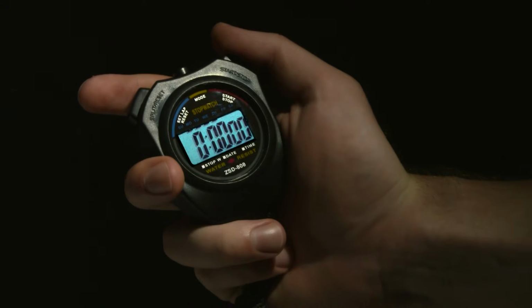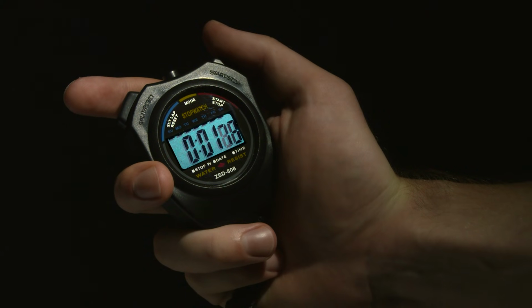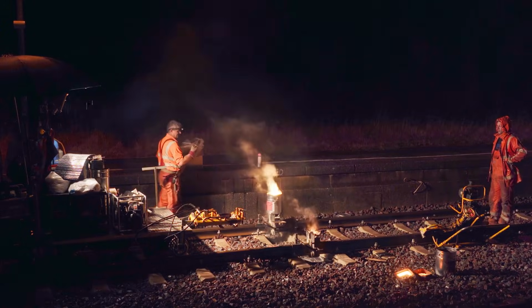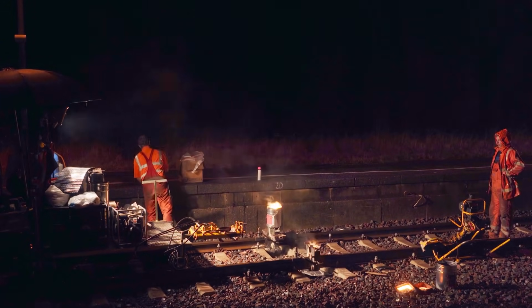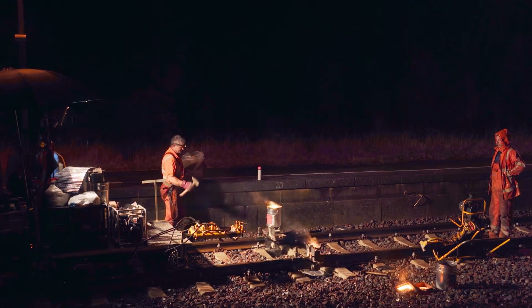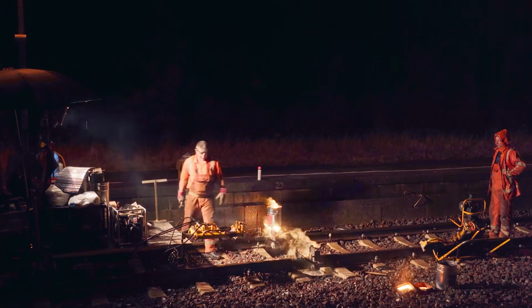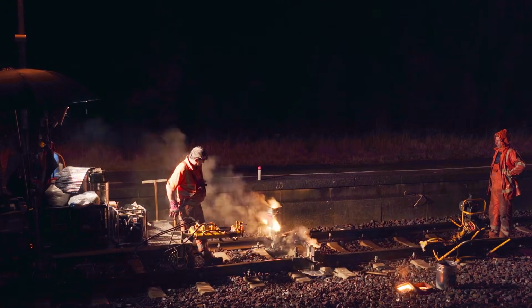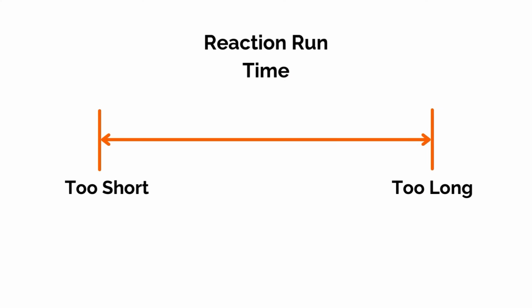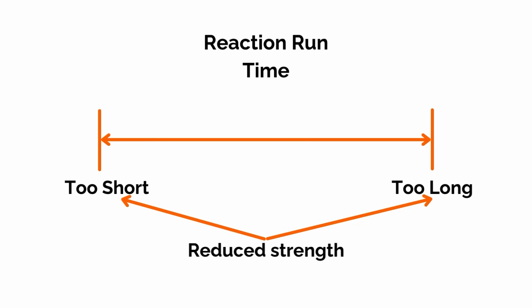After the aluminothermic reaction reaches full temperature, timing becomes everything. Once the reaction starts to run, welders don't interfere, but they do stay alert, monitoring the ignition, the duration of the reaction, and the way the molten steel flows into the mould. They're making sure the reaction runs for roughly the right amount of time before the pour begins. If the reaction ends too quickly or drags on too long, it usually means the portion hasn't burned as intended, which can reduce the weld's strength, disturb fusion, or alter the metal composition.